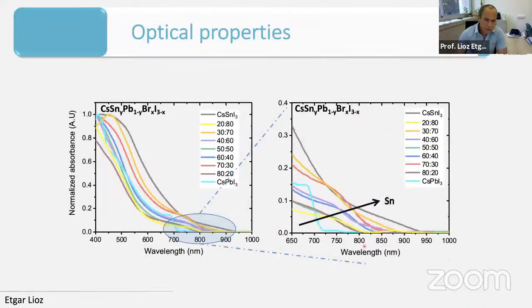So the first observation was very nice to see that when you add tin to the lead, which means instead of the lead you add more and more tin, you can push the absorbance through the near IR. If usually perovskite absorbs until, if it's all inorganic, 700 or 800, you can go even to 950, which is something obvious, which is good of course for photovoltaic devices, as you can see here. So this was one nice observation to get.